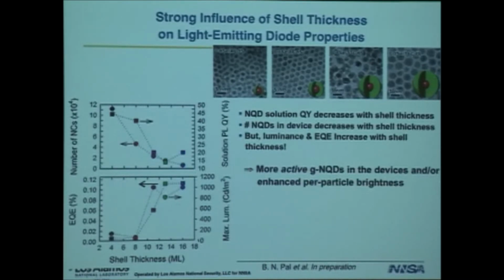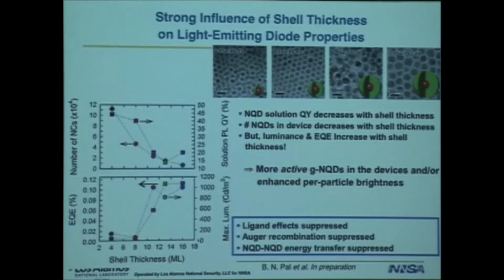We appear to have more active emitters in the devices as opposed to the solution phase, or we've enhanced the per particle brightness. We're not sure yet. But how could any of this be happening? Again, we look to the fact that if there are bad ligand effects affecting the thin shell systems, those effects are suppressed in our thick shell system. Auger, of course, is also suppressed.